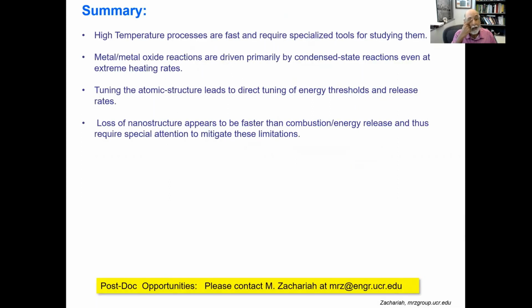So with that, I'm going to stop and say that, I hope I've shown you that these high temperature processes typically are quite fast and require specialized tools. These metal-metal oxide reactions are actually typically driven by condensed phase reactions, even under extreme heating conditions. And that if you knew enough about the relationship between atomic structure and microscopic behavior, that you could use that to tune thresholds and energy release rates.